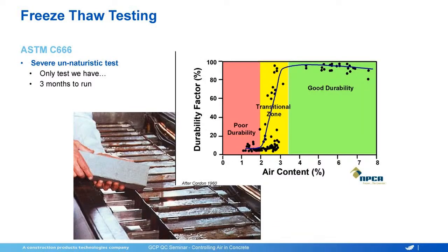Yeah, so C666, it is a very severe test, but it is the only test we have. It takes about 90 days to run it because you're cycling through 300 cycles of freezing and thawing. And what you'll see is, again, air content's low. You're almost always going to pass freeze thaw.